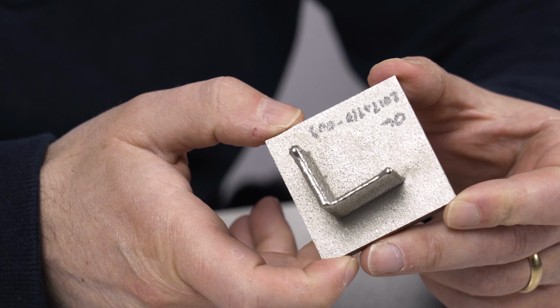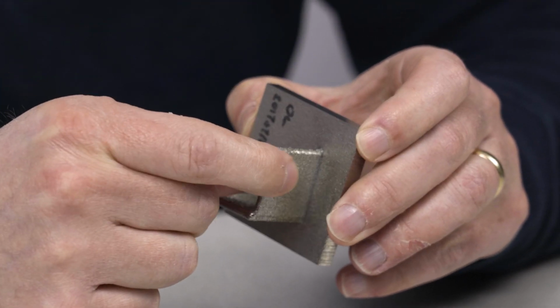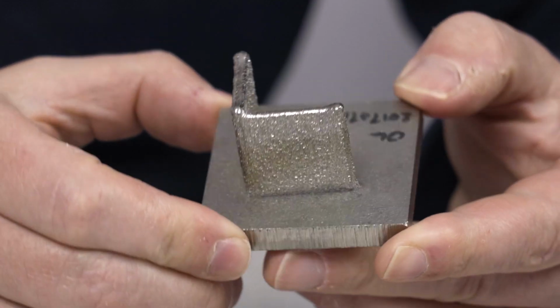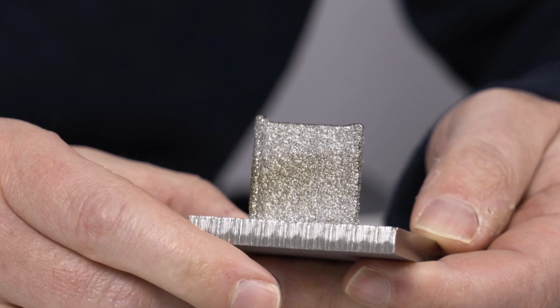So just in that simple one, if you are not changing power and speed as you go from a thin to a thick wall, the heat conduction, the heat transfer is going to be different, right? You've got more mass in a thicker wall than a thin wall. So if you're not adjusting your energy input, again, laser power and speed, then that difference in heat transfer is going to lead to different efficiencies in powder capture, which manifest in terms of different build heights. So a thinner wall is going to conduct it out. It's going to spread more versus a thicker wall. You don't get as quick a spread of the heat and it tends to build up a little bit higher as you go if you are not changing or adapting your tool path, essentially your deposition path, feeds and speeds in this case.